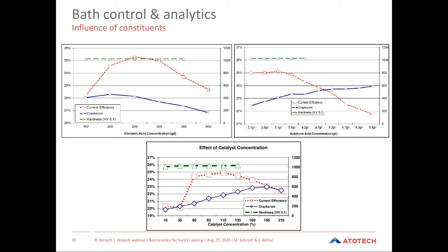As a rule of thumb, you can say if the chrome is coming out bright of the plating bath, the hardness is typically minimum 900 Vickers hard. Chrome only loses its hardness when it's heated up to more than 400 degrees, the layer, not the bath. If the layer is getting these high temperatures, the chrome will get softer.